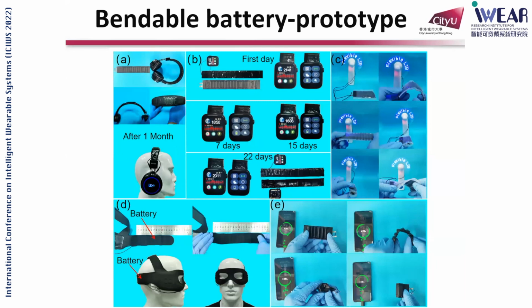Within 2 or 3 days it will be fine, but after 30 days or a few months, you will see more batteries get gas coming out. We guess that the SEI film is broken in this case. We are trying to develop tough SEI films in our lab, but it's much more difficult actually.